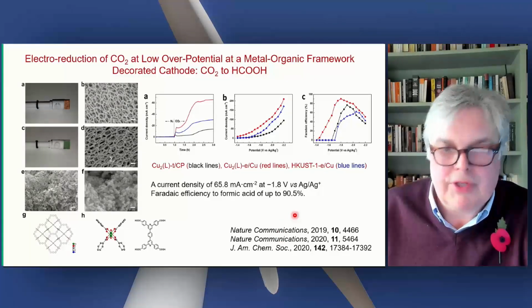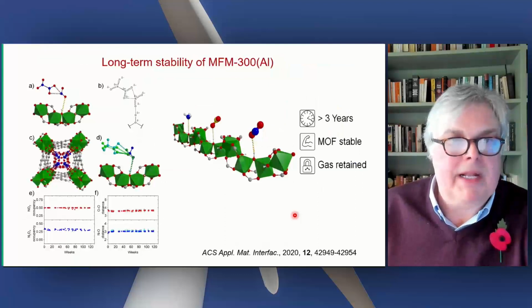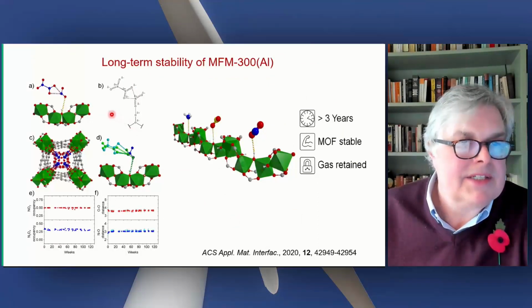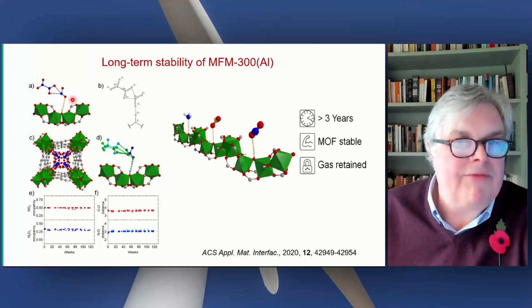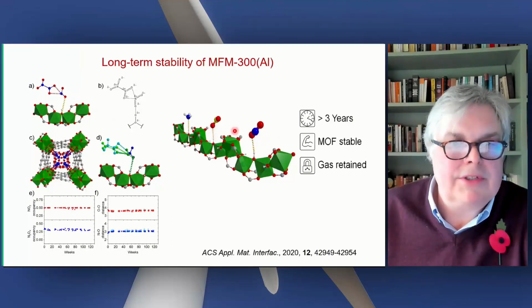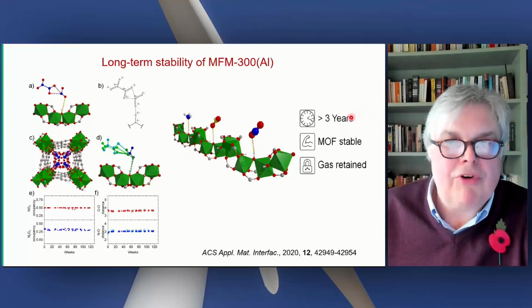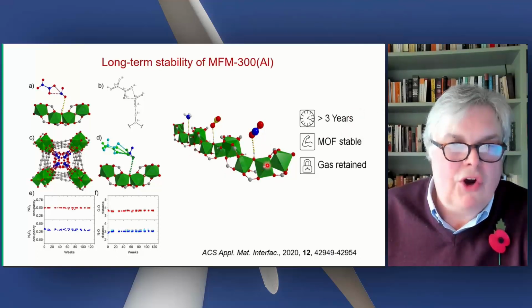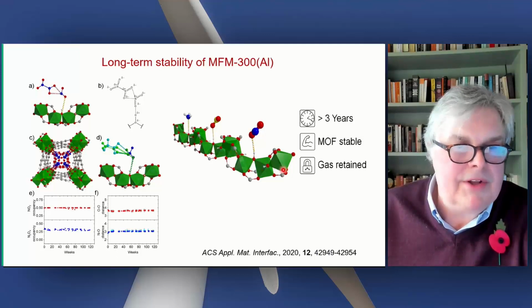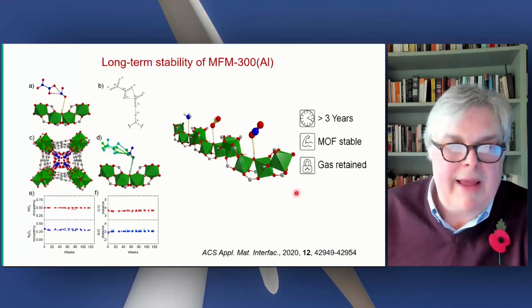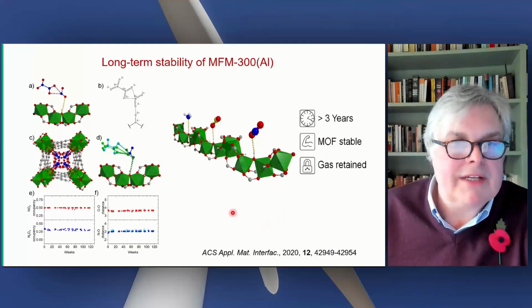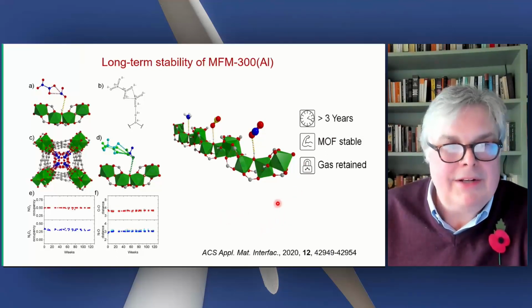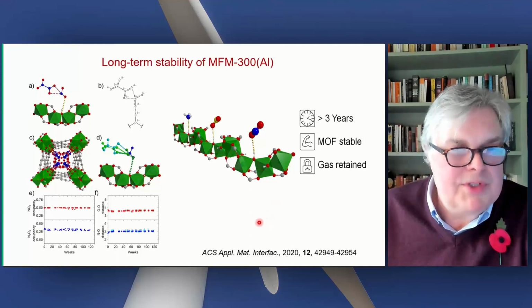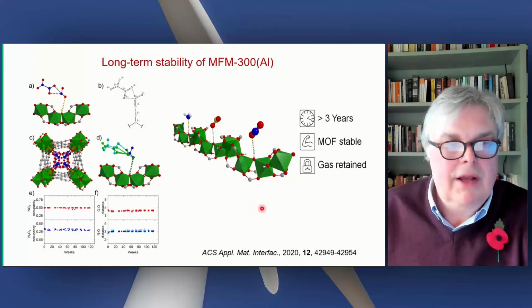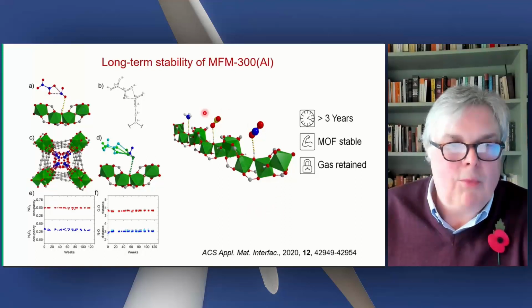to generate CO2 reduction products. And finally, to emphasize the stability point, we have now had samples of NO2 loaded MOF and SO2 loaded MOF, NO2, SO2, and ammonia loaded MOF at Diamond for 3 years now, and the structure has not changed. The material is stable under those conditions for 3 years. So I would emphasize there are some MOFs that really are as stable as zeolites and really can do catalytic chemistry, substrate activation, substrate separations. Of course, not all of them are this stable, but we can do this.